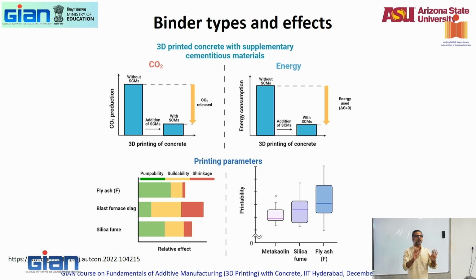Okay. Now, if I want to control viscosity, what are my options? Does any of these particles change the viscosity? No. Right? Do admixtures change viscosity? Yes. Which admixture will change it? A viscosity modifying admixture will change the viscosity. So if I have to really change the viscosity, and that's why in a lot of 3D printed mixes, you will see people using viscosity modifying admixtures because they have to control the viscosity in some fashion, right? Yield stress, you can play around with particles nicely. Viscosity, you have to use a viscosity modifying admixture. So now you have all these different options that you can play around. So you reduce the cement content, you can play around with all of these.